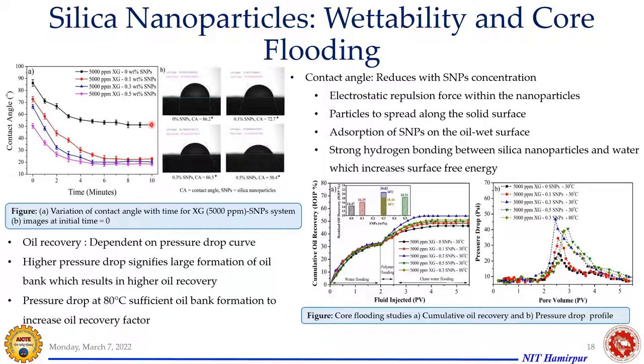So you can see here oil recovery. Okay. Before we do the oil recovery, we change the contact angle. You can see here, as we keep on increasing the nanoparticle concentration, the contact angle reduces at the very starting point, that is at t equal to zero. This is 86.2, which is no nanoparticle. When the nanoparticle was 0.1 weight percent, it is 72.7. When the nanoparticle was 0.3%, it is 66.5. And when the nanoparticle concentration is 0.5, it is reduced to 50.4.